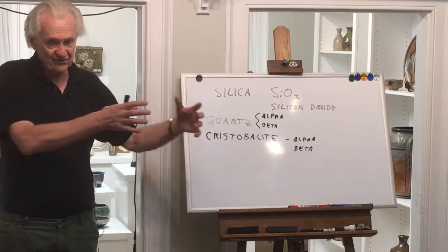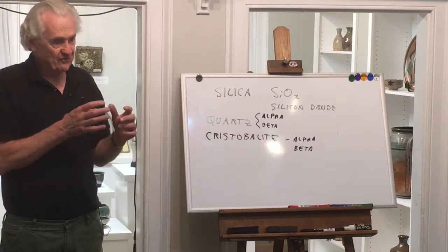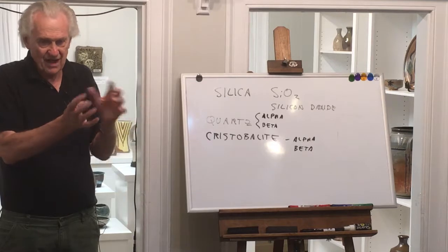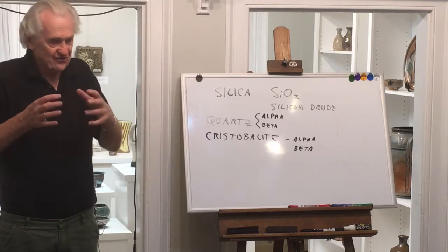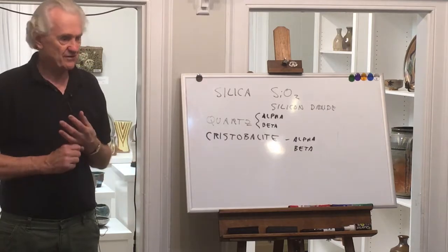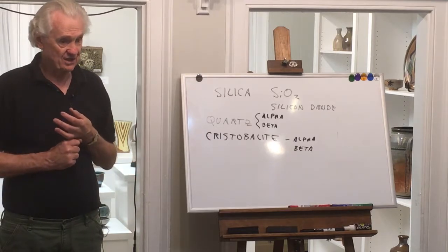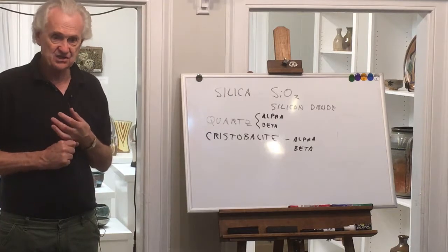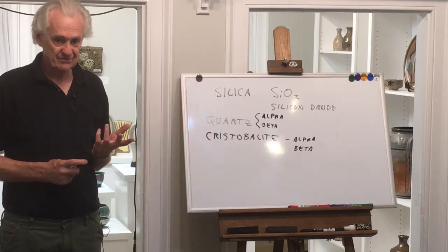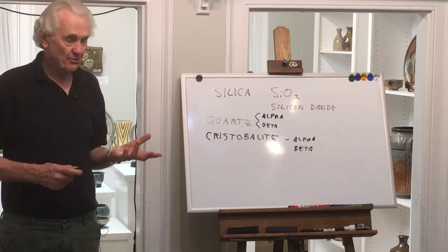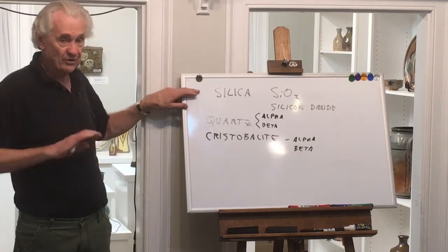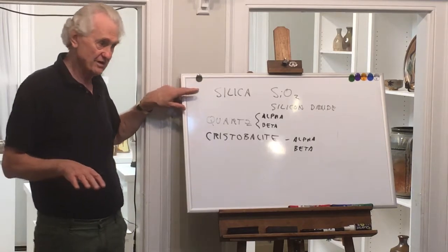Clay forms from pre-existing rocks, and those pre-existing rocks almost always contain quartz. Well, when the rock is modified and changes into clay, the quartz just comes along with it. So there's quartz everywhere, basically. You're all familiar with the term MSDS, Material Safety Data Sheet. If you look at a data sheet for ball clay, it says that the ball clay can contain up to 30% quartz. So what you think is pure ball clay isn't even pure clay. It may have up to a third of quartz in it. Totally different material, totally different mineral, okay?